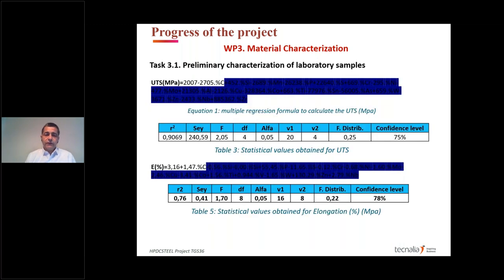And from all this, we obtain a formula where we have an estimation of all the properties in function of the composition of the alloy, in the range of alloying elements that we employ for the matrix design. And with the obtained results, applying multiple regression formulas, we obtain some formulas. But the main thing that we have from this was that the regression coefficients were very, very high.